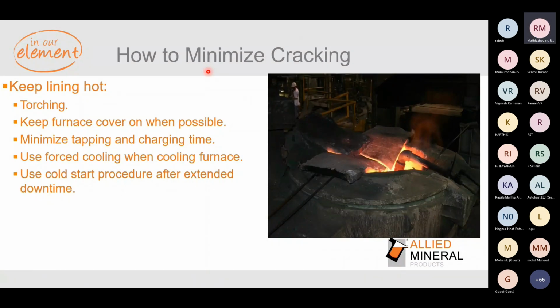There are certain people actually who do this to minimize the cracking. They always keep the torch on, so they put a burner and they keep the lining hot. They keep the furnace closed whenever possible. Minimize the tapping and charging time. As I said, forced cooling is what we recommend, and cold start procedure after extended downtime.